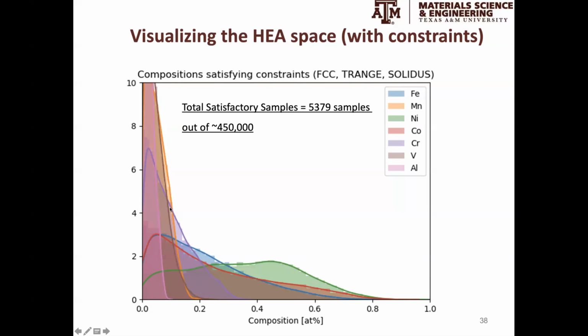The same applies with chromium. We see a distribution peaked at around 5% chromium, but we can say with certainty that in the universe of feasible alloys, there's no alloy with more than 30-something percent chromium.